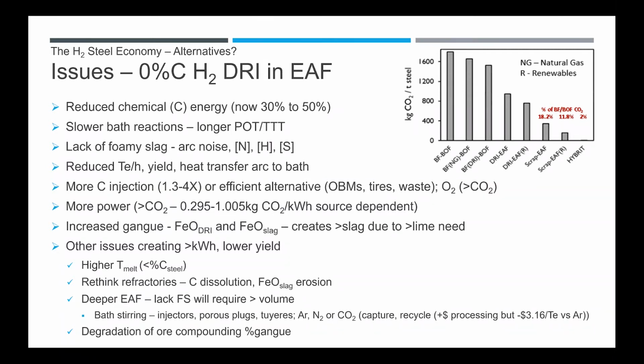And the other issues which would create more kilowatts and lower yield are going to be, you need a higher temperature to melt if you have less carbon. You're going to have to rethink the refractories because there's going to be carbon dissolution and erosion from the slag FeO. You're going to need a deeper bath because without the foamy slag, you're going to need a greater volume, and that's going to require bath stirring, and most of the steel makers have been fighting using that for a long time. And again, we have degradation of the ore, which will compound the gangue issue.